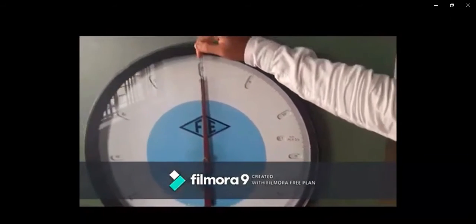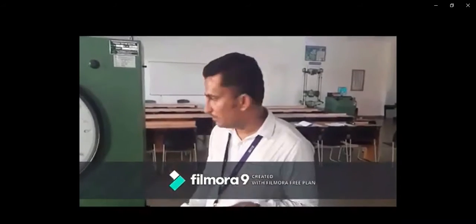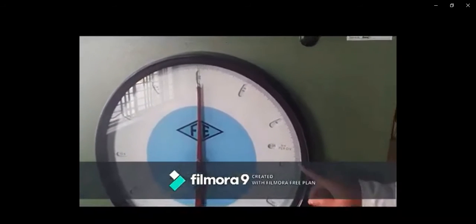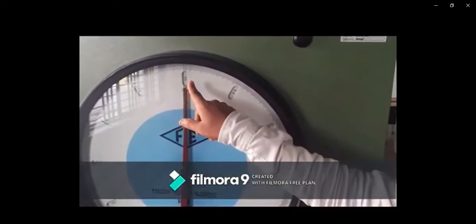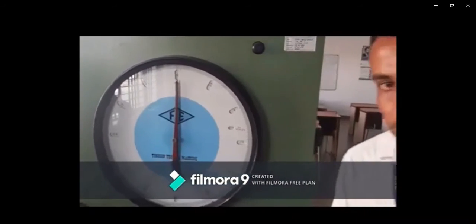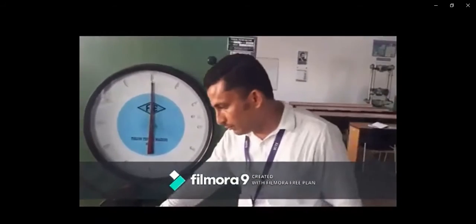So the maximum torque that can be measured in the 0.1 scale is 60. But in the 0.05 scale, you can measure the maximum torque as 30. So for this mild steel specimen of 6 millimeter diameter, a scale of 30 Newton meter is enough. Means 0.05 scale is enough. So that's why I'll change it to 0.05 scale. Yeah, now 0.05 scale. Maximum torque that can be measured by the scale is 30 Newton meter. Now we have to fix the specimen after setting the scale.